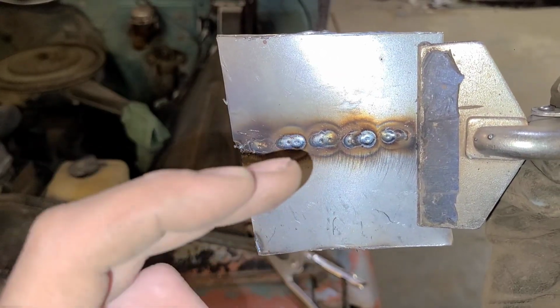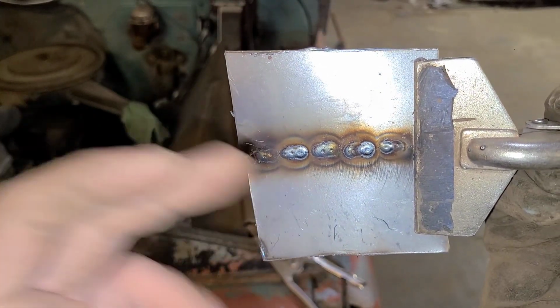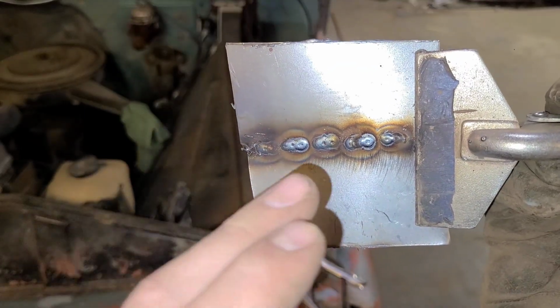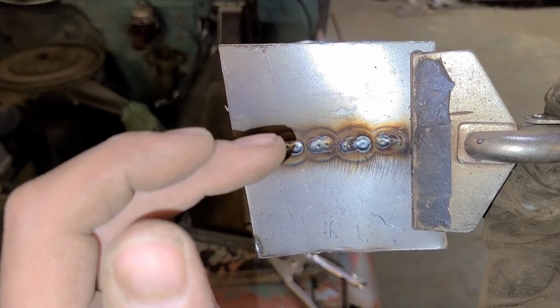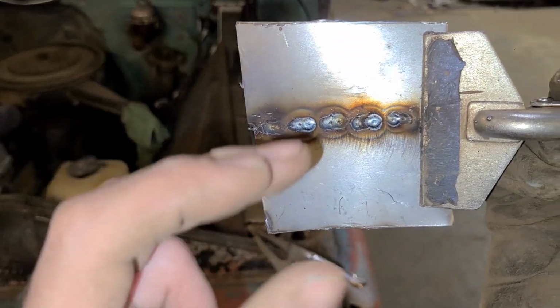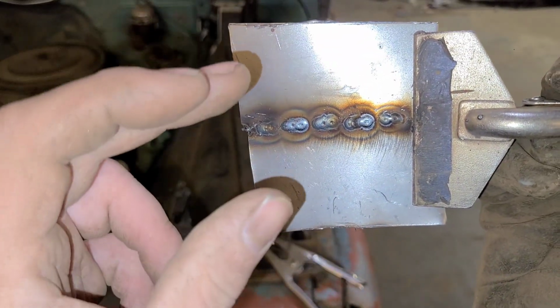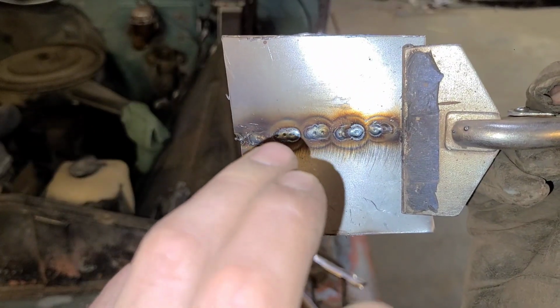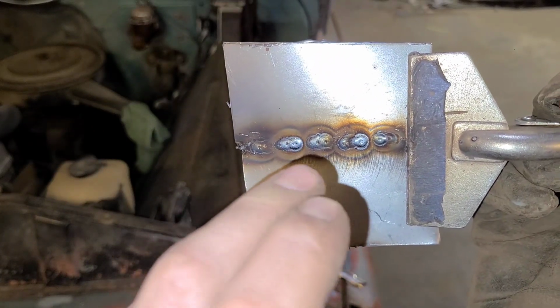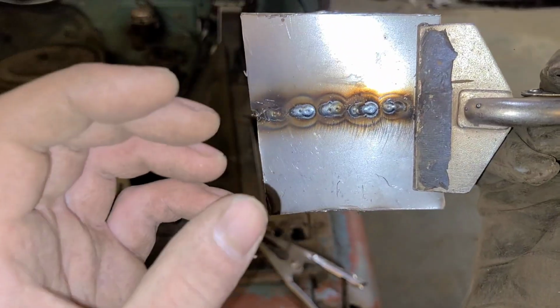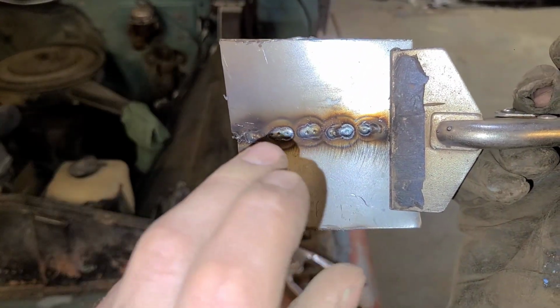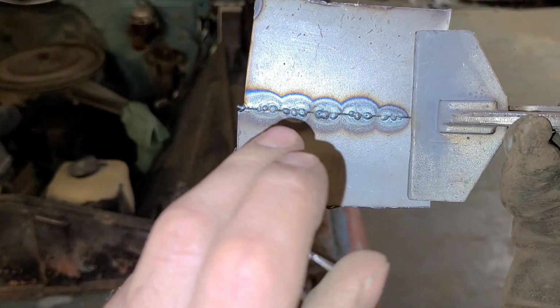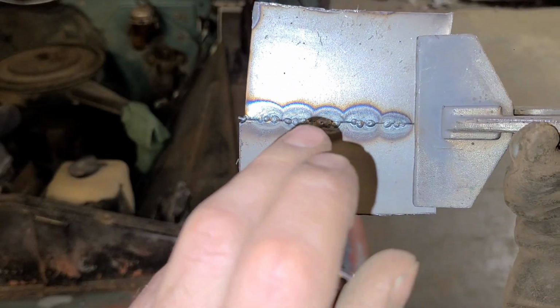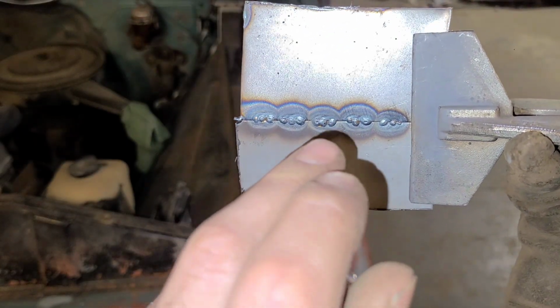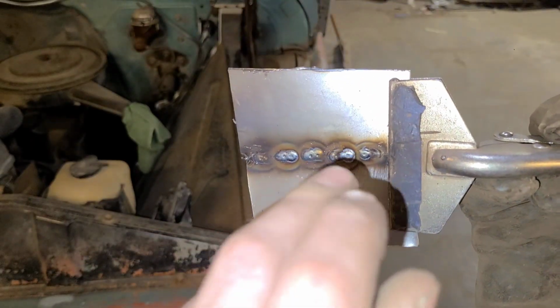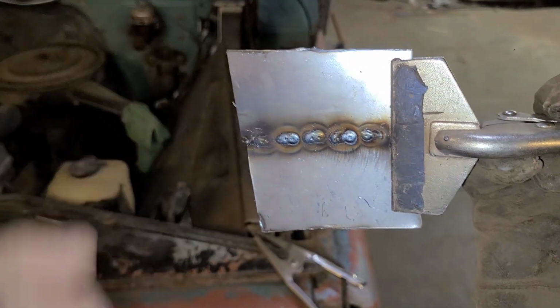Now if you use an auto darkening helmet, I don't recommend using anything other than an auto darkening helmet. It makes it so much easier to see, and you can see the red weld. And the longer you wait between doing your tacks, the colder the weld will be. So this one, I waited barely any time at all between each tack, so it was still very molten and very, very hot, and I could see that this technique gave me the best penetration. All the little dots on the back are all connected together, whereas all these other methods, I was waiting too long between each weld, so it was leaving it cold.